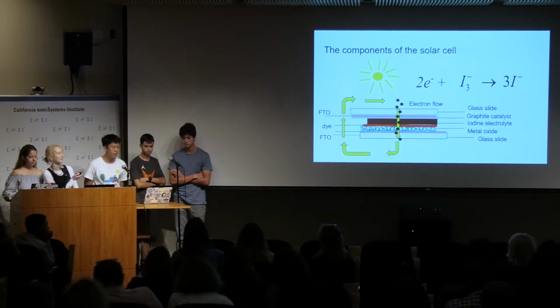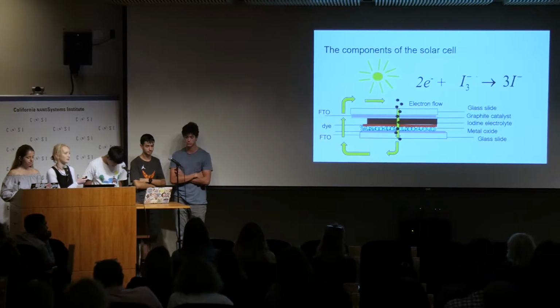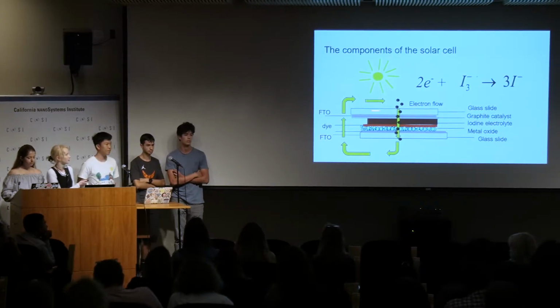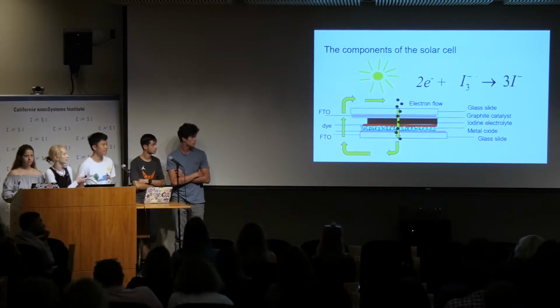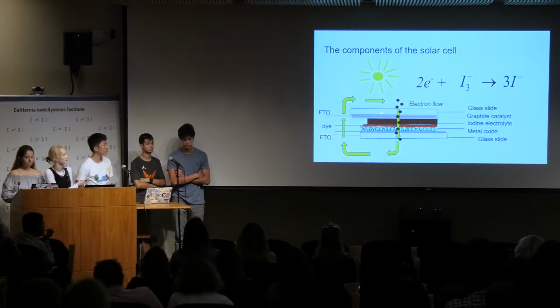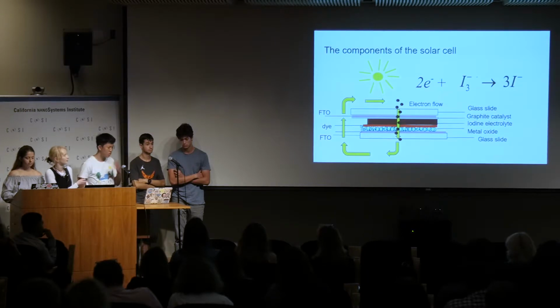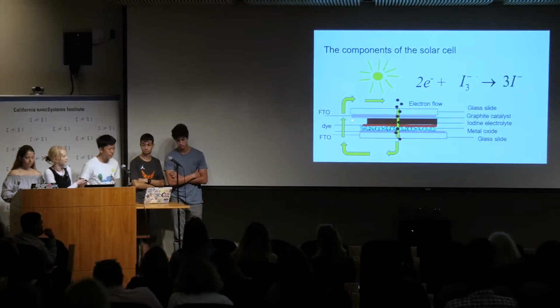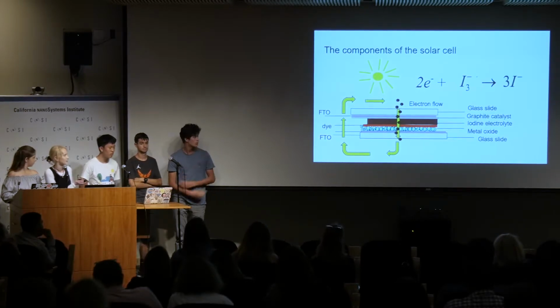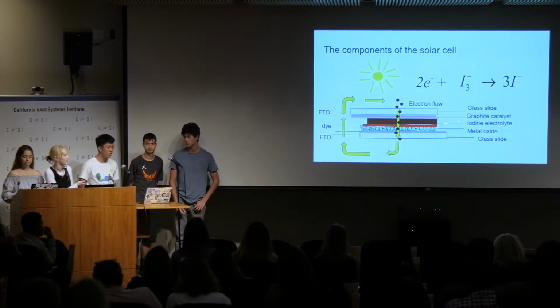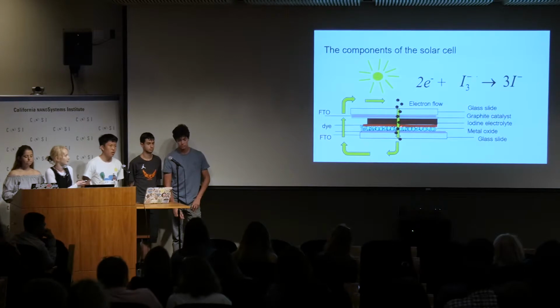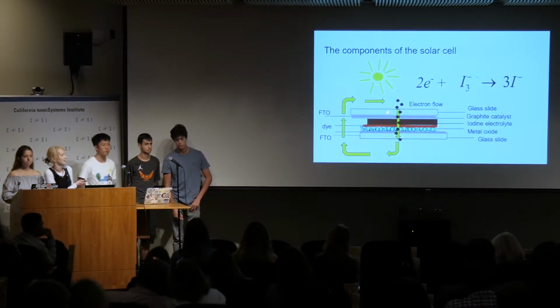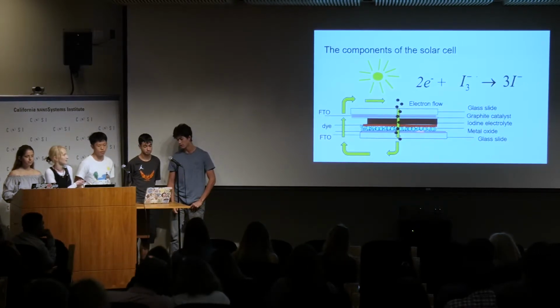So this is a diagram of our solar cell that we constructed in our lab. So on the white layer here and the white layer here is our glass slides, and there's a thin layer of fluorine-doped tin oxide on top, which serves as the conductive layer. And right over that is the graphite catalyst, which lowers the activation energy for the redox reaction of the iodide electrolyte. And then underneath that is the anthocyanine dye, which underneath that is the metal oxide, which is the semiconductor.